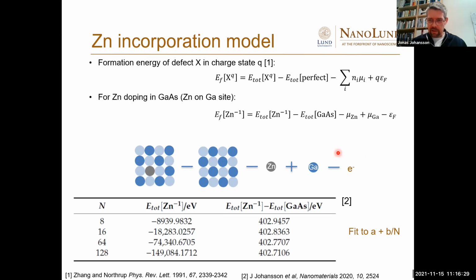This means that there is nothing left. The only thing left is the sort of excess energy, that is the formation energy of this defect. That is the only contribution left. We have subtracted all kinds of atomic or bulk energies. Only the formation energy is left. We should calculate this and this total energy here for some different sizes. As many as we can, of course, but it's more and more expensive for a larger and larger supercell.